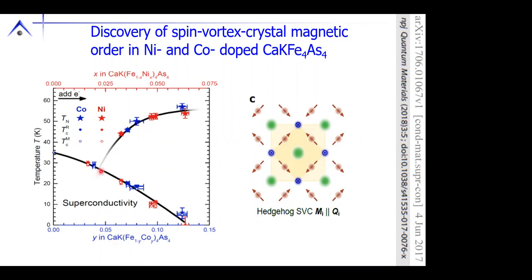Secondly, there's a new phase line here, and we were able, through detailed measurements of NMR, Mossbauer, structural transitions, thermal expansions, ultimately neutron scattering, to identify this as a new type of magnetic order for the iron arsenide, something called a hedgehog spin vortex crystal, which very importantly has no structural component to it, so no nematicity.